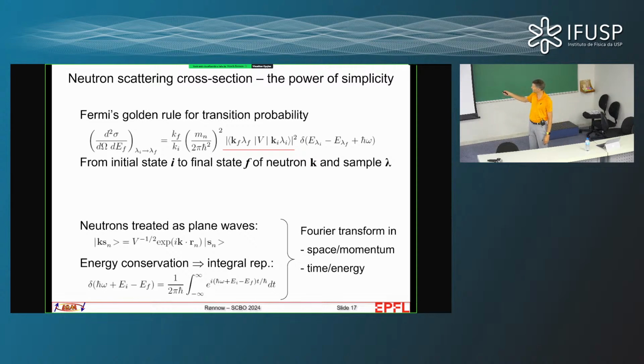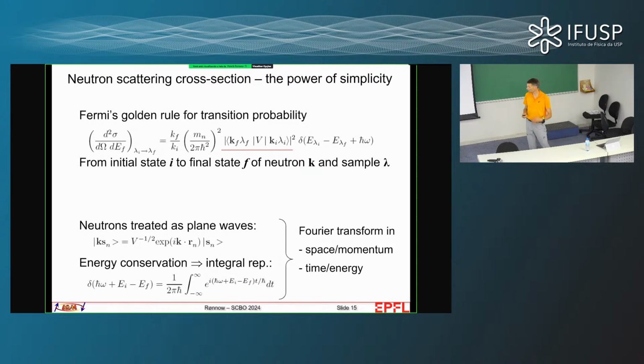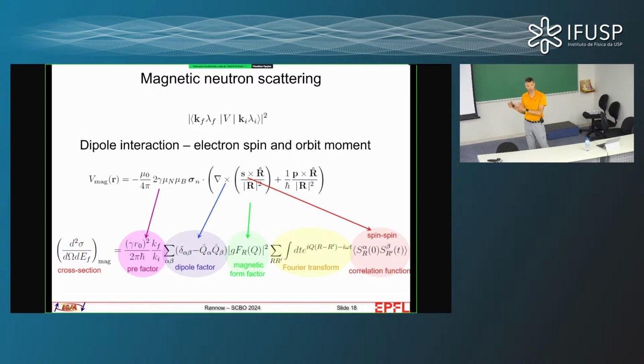So basically the energy transferred by the neutron has to be equal to the difference between the initial and final energy of the sample. So this is a delta function, but mathematically I can write down this delta function as such an integral, and you will notice that this integral becomes a Fourier transform with respect to time. Okay? So that means that what we measure is a Fourier transform with respect to space and time of the interaction between the neutron and the sample.